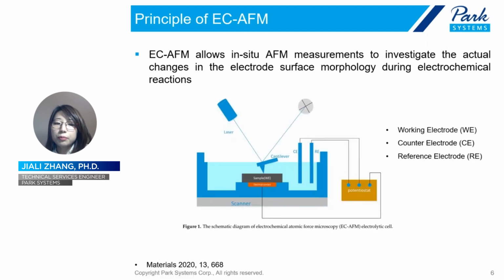The basic working principle of EC-AFM is very similar to that of AFM and shares the key components. We have a sharp tip, an XYZ scanner, and a feedback control system, as shown in the diagram of a typical EC-AFM. In addition, EC-AFM requires an EC cell that can accommodate the working electrode, which is usually the sample, and the counter electrode and reference electrode, as well as a potentiostat that controls the applied potential of the sample that controls the interfacial reactions. During the scanning, the sample is placed in here as a working electrode and the EC reaction is happening here. And then by scanning the tip, the force between the tip and sample is measured by monitoring the deflection of the cantilever to obtain the topography or morphology changes of the sample during EC reactions.